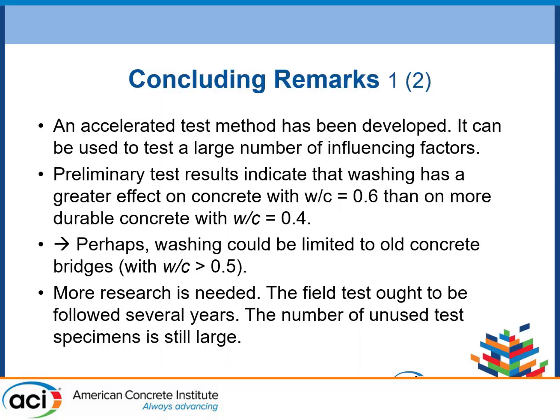And I thought I had another, because it says 1 out of 2. But this is 2 of 2. Yes, an accelerated test method has been developed. It can be used to test a large number of influencing factors. Preliminary test results indicate that washing has a greater effect on concrete with water-cement ratio equal to 0.6 than if you are using a more durable one.